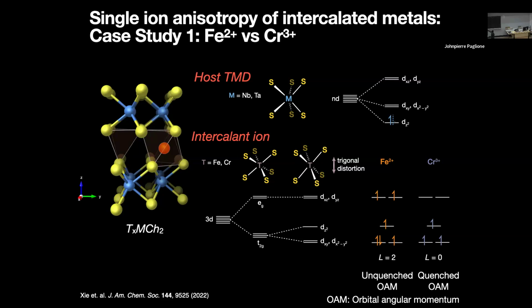And what that does is it's going to split the T2g yet again. The model you could think of is that the dxy and dx squared minus y squared are the lowest lying orbitals, then you have the dz squared next, and then the dxz and dyz are the highest. And so what that means is that for transition metal ions like iron and chromium that have different numbers of d electrons, you end up with very, very different extents of quenching of that orbital angular momentum.